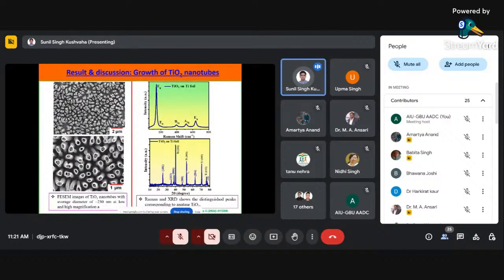So, for example, after growth, we have to characterize our systems with different techniques. Like, this is our SEM images. From here, we can see the formation of these TiO2 nanotubes. And when we measure the diameter of the TiO2 nanotube, it comes to around 200 to 250 nanometer. And then of course, other techniques to characterize the structural and crystalline property. We have Raman and XRD measurements, which can clearly show the formation of TiO2.